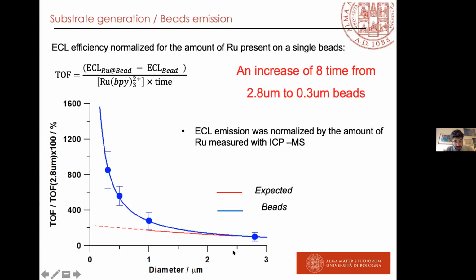quantification of the ECL efficiency for the 2.8 micrometer beads commercially used, we have this emission, and after that we go to this exponential increase. So if we concentrate for smaller beads like 0.3 or 0.5, with 0.3, for example, we can have an increase of the signal of 8 times, because in that region the ECL is more active, it is the more active part of the emission.